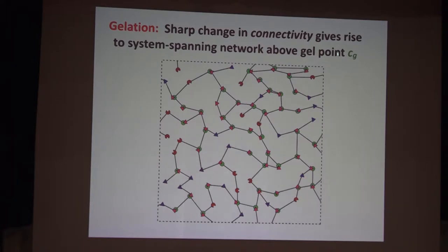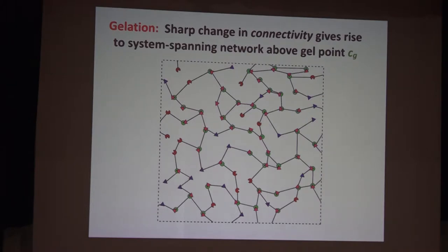Here is a synthetic example of something Mike studied: multiple SH3 domains connected by linkers that bind to ligands that are also multivalent, having multiple proline-rich modules connected by linkers. When you think about these types of associative polymers and physical crosslinks, the first thing that comes to mind is that these physical crosslinks can cross a threshold network — a percolation threshold — whereby most of the molecules become part of a system-spanning network, which we refer to as a gel. The bulk concentration above which that gel point is crossed is called the gel point concentration.